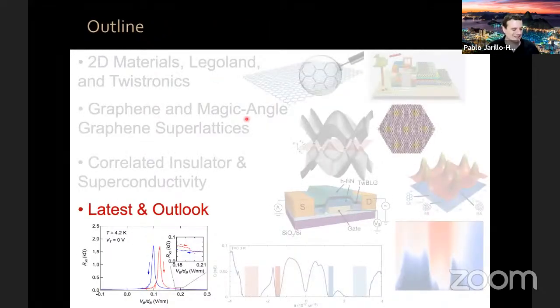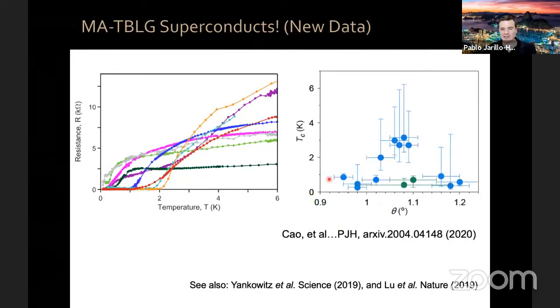Now, in the last 10, 15 minutes or so, let me tell you about some of the latest things that we have been looking at. So we published our discovery in April 2018, okay? And lots of things have happened since. First thing that happened is that we have reproduced our own results many times. Believe it or not, it doesn't always happen that you reproduce yourself, so it's very good that we did it. We have by now many, many more superconducting devices. Actually, these are even old, we have many more by now. We're in fact starting to measure optimal doping DC critical temperature as a function of twist angle. So we have a dome here also in twist angle. And as you can see, superconductivity occurs primarily between about 0.95 and 1.2 degrees.